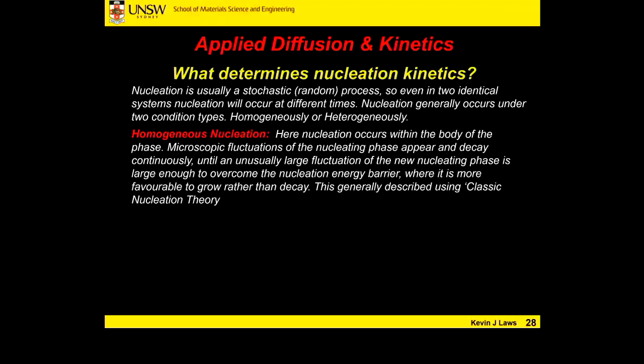And we'll get onto this in a little bit more detail next week. These microscopic fluctuations of the nucleating phase appear and disappear continuously until we get an unusually large, random fluctuation of the new nucleating phase, which is large enough to overcome the nucleation energy barrier, where it's more favourable to actually grow rather than decay. We can describe this process using classical nucleation theory, which we'll do next week. But yes, there's an energy barrier for nucleation.